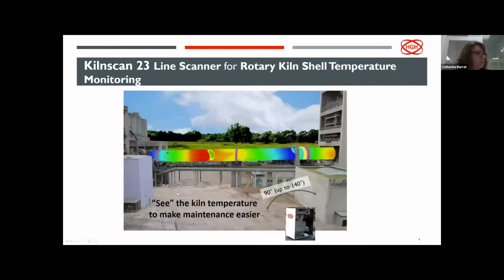What is the principle of the kiln shell scanner for rotary kiln shell temperature monitoring? A kiln shell scanner is a line scanner measuring the temperature over one line along the kiln shell. And as the kiln is rotating, we thus obtain a full temperature image of the kiln shell, taking into account that the scanning speed is 25 Hertz, meaning that this line scanner measures one line 25 times per second. So, using the kiln rotation, we obtain a temperature map of the kiln shell.